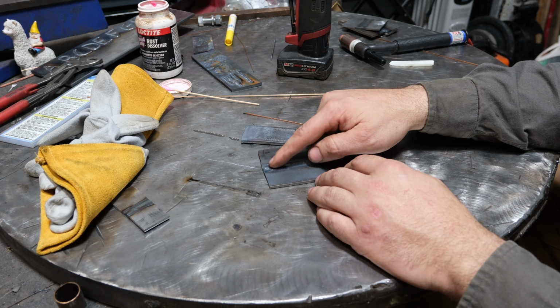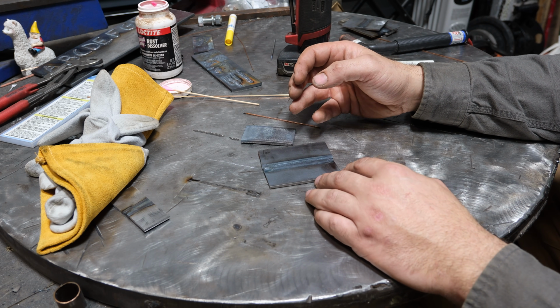When you don't do that with TIG, all of that material winds up in your weld pool, and then it gets deposited on the surface, or worst case, inside of your weld, and that can be a detriment. It can create things like porosity, but it can also make the molten puddle flow out poorly.